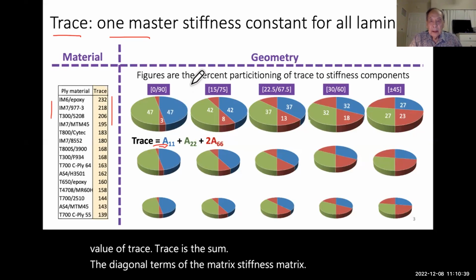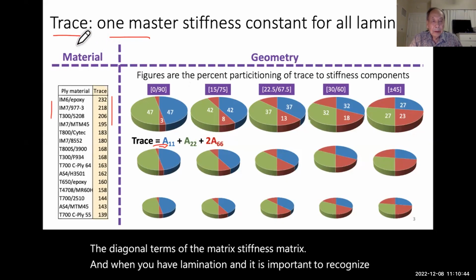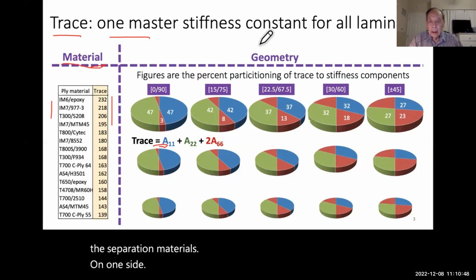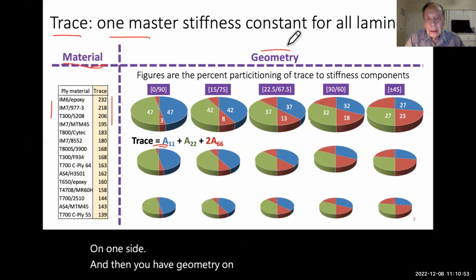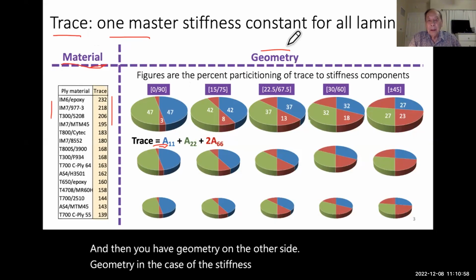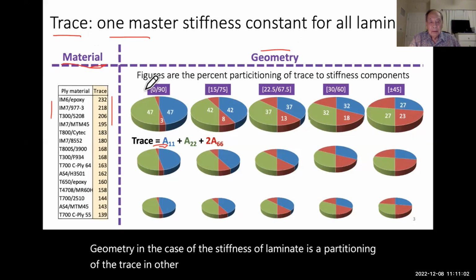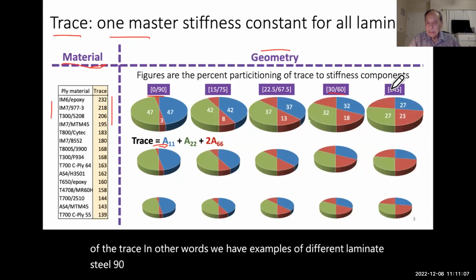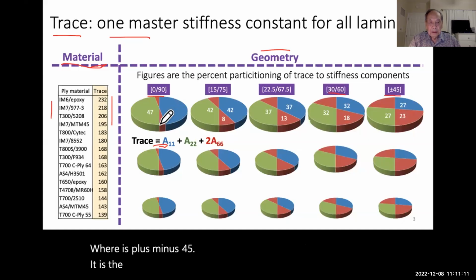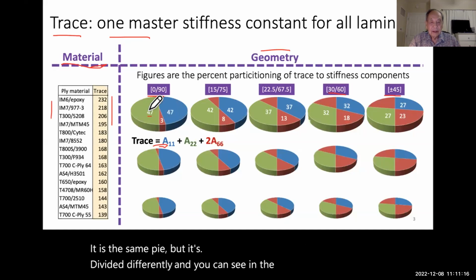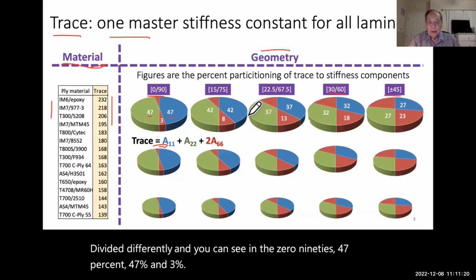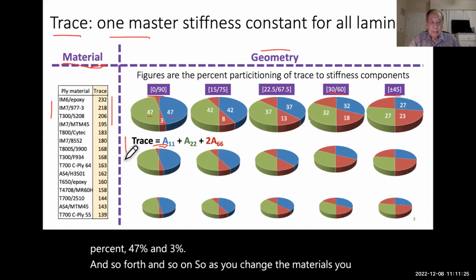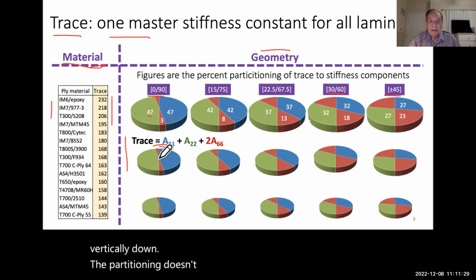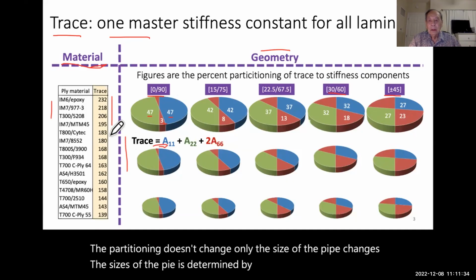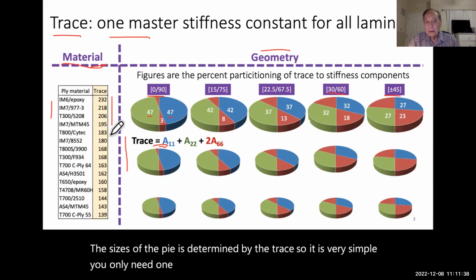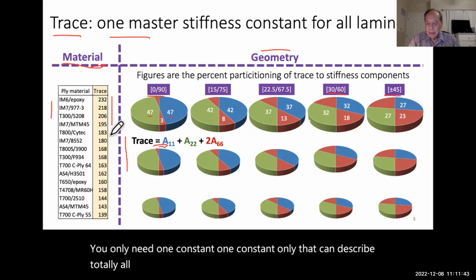And when you have lamination, it is important to recognize the separation: materials on one side, and then you have geometry on the other side. Geometry, in the case of the stiffness of a laminate, is a partitioning of the trace. In other words, we have examples of different laminates, 0, 90, and various plus minus 45. It is the same pie, but it's divided differently. And you can see the 0, 90 is 47%, 47%, and 3%, and so forth and so on. So as you change the materials, you go vertically down. The partitioning doesn't change. Only the size of the pie changes. The size of the pie is determined by the trace. So it is very simple. You only need one constant that can describe totally all the stiffness of laminates.